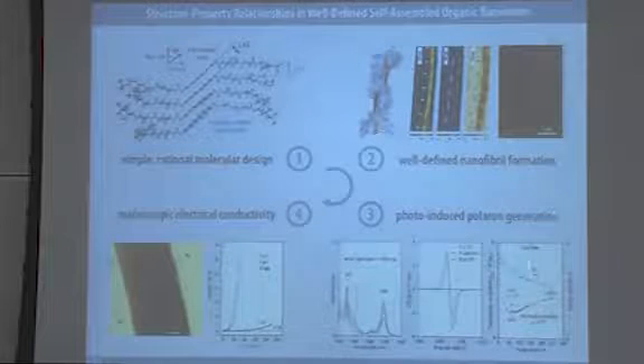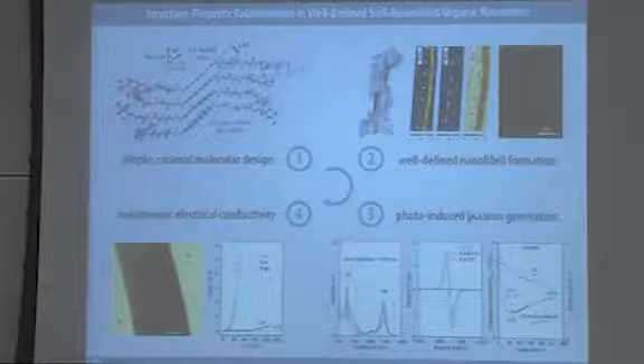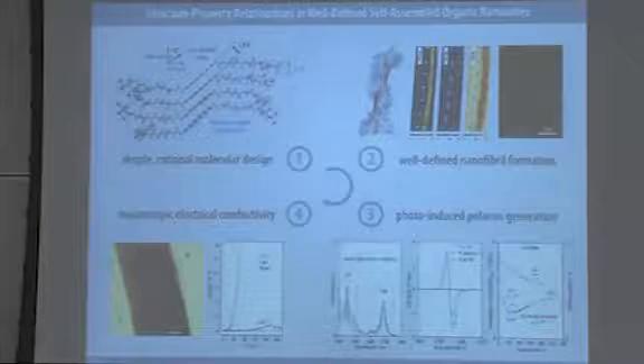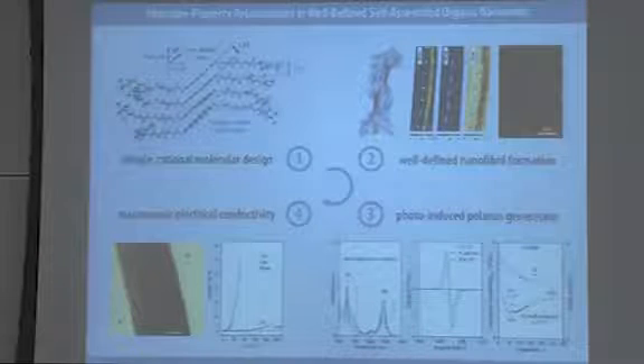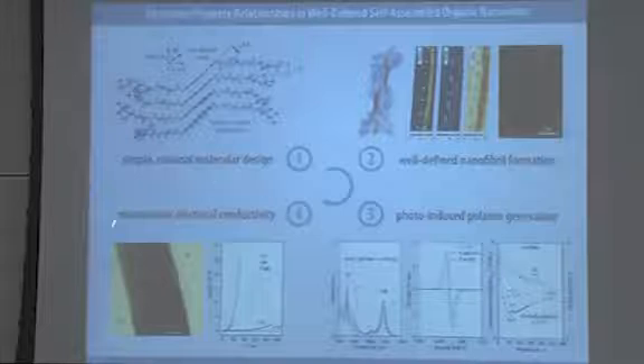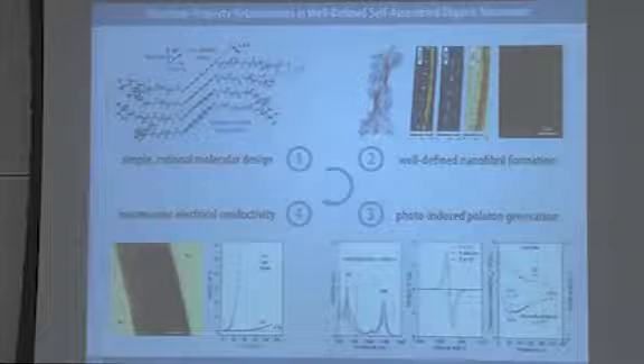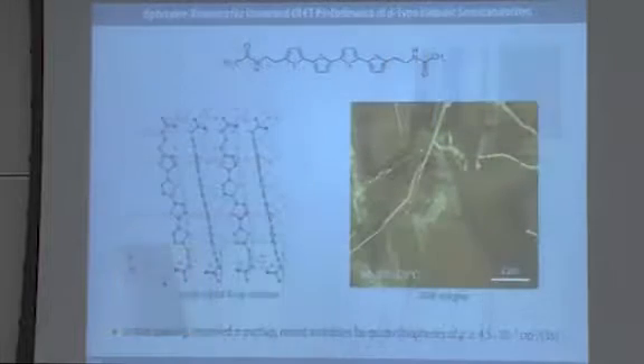I hope I've been able to show you that this is then responsible for the unprecedented formation of long-lived radical cation charge carriers in the absence of a dopant, and that the macroscopic conductivity observed in these cases can be attributed to those systems. This is my last slide.